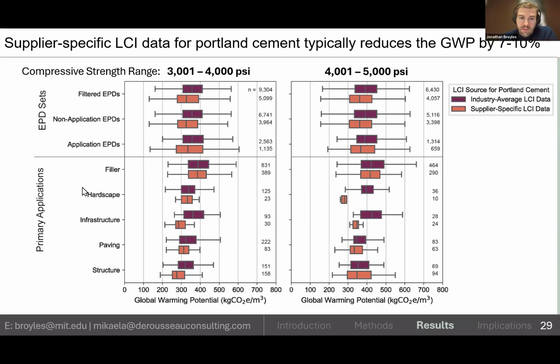It was interesting. Several of the different applications had almost the same median GWP, looking at filler across both of the different strength class ranges, hardscape in the 3,001 to 4,000 strength range, even similar for paving, and then structure for 4,001 to 5,000 PSI. So again, none of these different sub-analyses fully explained the differences in the application GWPs. So truly what we're thinking then is there are differences likely just due to the inherent differences in the mixtures for these different application types.